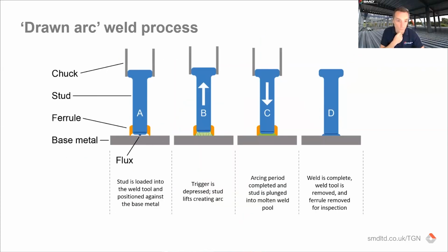So the drawn arc weld process, using that gun with the chuck of the gun at the top here, you have the ferrule laid out, you have the stud position, the stud is loaded into the gun, positioned against the base metal. When the trigger is pulled, it pulls the stud away, which is the lift setting. That lift ignites the arc. The arc then heats up the top flange of the beam in a molten weld pool, and then, for want of a better word, brute force straight down into that weld pool, which ultimately then creates your weld, and the ferrule is what then contains the weld around the foot of the stud.